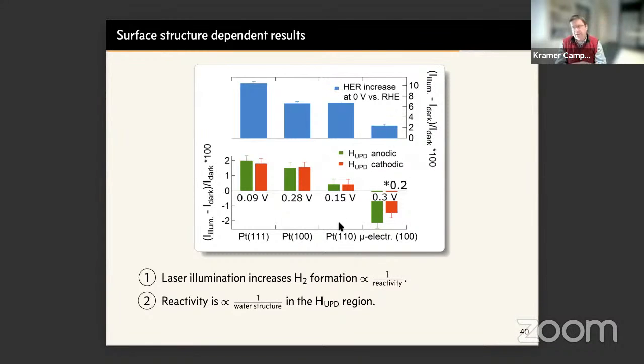So where does all of this leave us? So I show you 2 trends in this current behavior. It is interesting to note then that this laser illumination increases H2 formation for all of these systems, but that the extent to which it increases H2 formation is inversely proportional to reactivity, right? So the microelectrode is more reactive for H2 production than the 110, then the 100, then the 111.